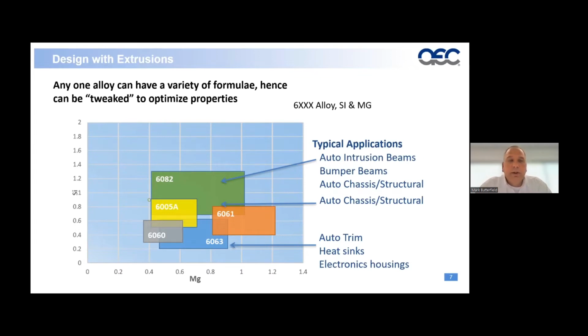significant starting point. As we see with 6082, which tends to drive a higher billet premium, we have additional costs there where we may be able to utilize a 6005 alloy, little less cost, little less quench sensitive, may drive a little bit better tolerance. But all alloys have their place. And within these alloys, there's significant variations.